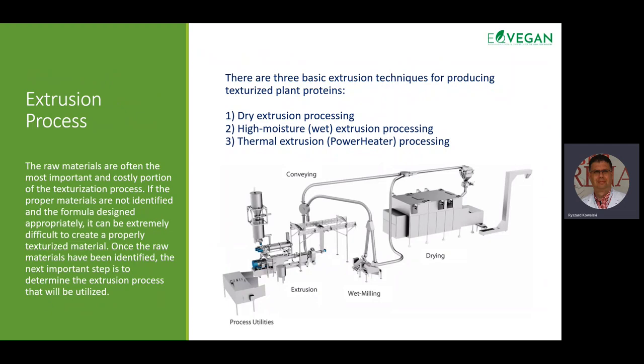Dry extrusion processing is the most common method utilized to create texturized proteins for several reasons, including the fact that it allows the widest range of raw materials, has the broadest flexibility in creating texture, and it is the most cost-effective method for the production of high volumes of the products. Typically, this process will operate with an extrusion moisture level of 20 to 35%, followed by drying to create a shelf-stable moisture content in the final products.